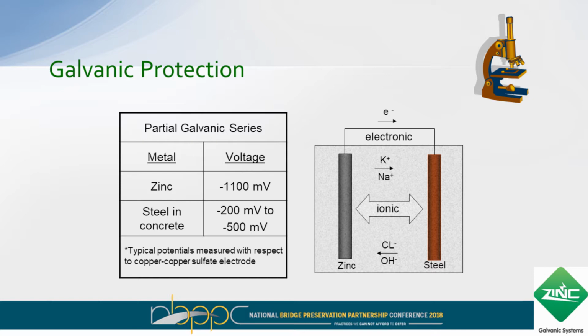It's connected to the reinforcing steel, and you see a typical range of potentials for reinforcing steel. For example, if you have a 500 millivolt potential at the steel, you may have 500 or 600 millivolts of driving potential to provide this electrical current. So you have the electrical path for the electron flow, but you also have an ionic flow through the concrete. The more moisture you have in the concrete, the more conductive it is, and the more current will flow between the two metals. Over time, the zinc is giving electrons off, it's corroding, it's reducing its metallic mass, and that current is used to protect the reinforcing steel.